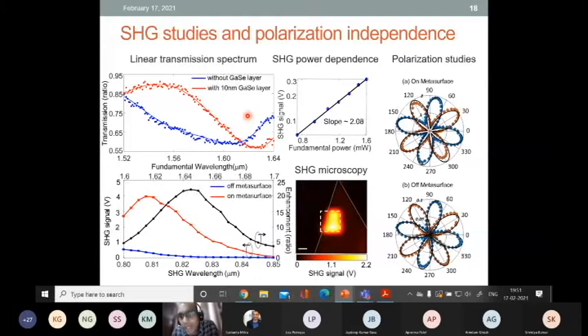And we obtain very similar polarization dependence when we selectively collect only the zeroth order diffracted angles. If we collect any higher order diffraction, then we see that these plots get distorted, or polarization dependence starts to set in. And we also characterized how much enhancement we can get in the nonlinear optical process. We were able to observe about a factor of 20 to 25 times enhancement in the second harmonic generation process, right on top of the metasurface. When you go away from the metasurface, the signals become very weak.